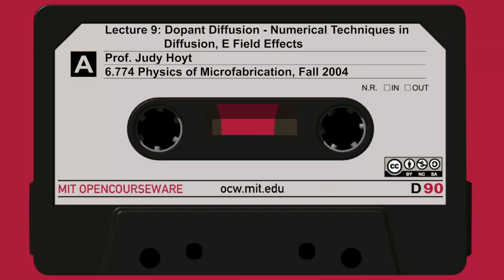Given that there's a relationship between N, the carrier concentration, and the concentration of the dopant C, because again the concentration C is just Nd minus Na, so it's the net concentration. So we have a relationship between N and C. We're going to use that to make this flux equation F to be written only in terms of the concentration C. So we go on to the next page, slide 21.